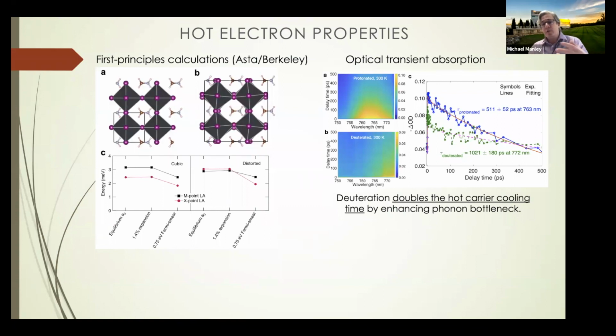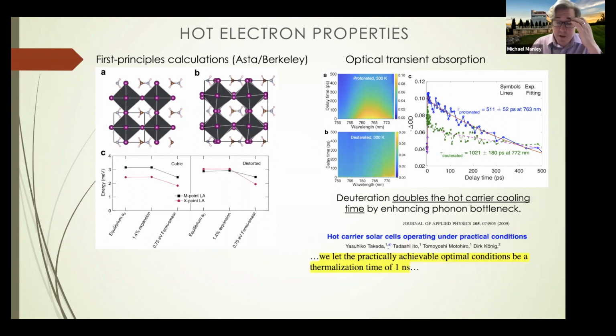So the deuteration doubles the hot carrier time by enhancing the phonon bottleneck effect on the charge carrier. So that was exciting. So I'll just say, what is 1 nanosecond? For context, this was a paper written a few years ago, in 2009, where they had said, okay, this is kind of a critical look at hot carrier solar cells. And they said, we'll let the achievable, optimum possible condition for the thermalization time be 1 nanosecond. So we're at 1 nanosecond, so that's pretty nice.